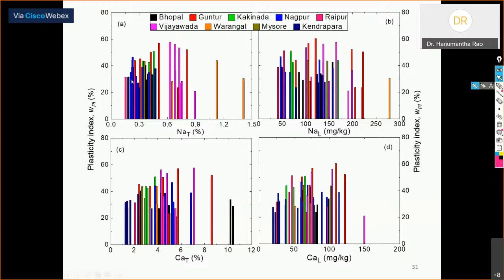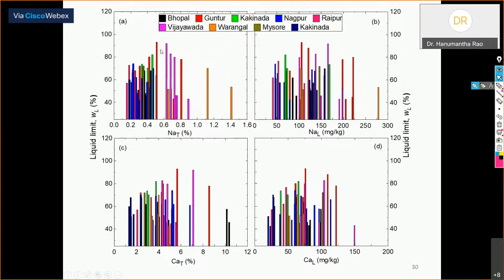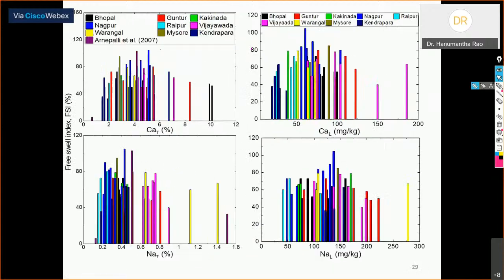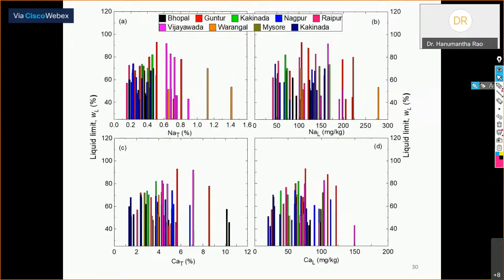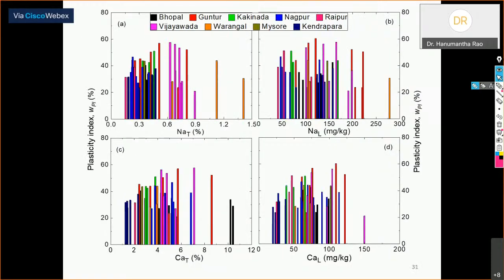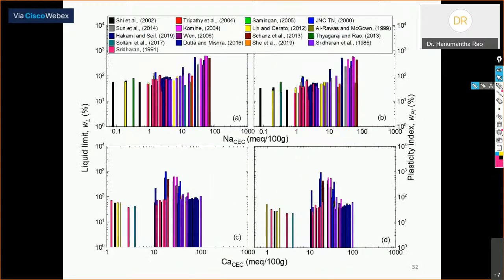So there is an increment in the plasticity index. You can see there is a perfect increase in free swell index, increase in liquid limit, then increase in plasticity index. They increased, reached a peak, and then decreased. So there is a beautiful trend. These are the relationships we got with the exchangeable form.